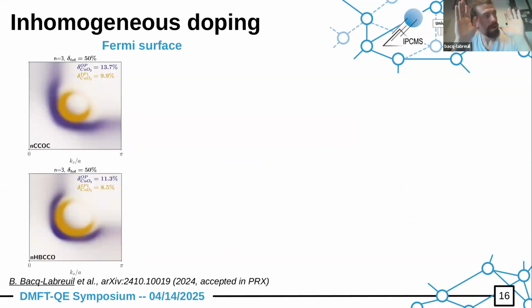Okay, so we have understood quite well what is intrinsic to this system, even before we dope. Now we can look at the normal properties. How do they behave when we dope the system? I think a nice way to see how the doping becomes inhomogeneous is to look at the Fermi surface. Here I plot the Fermi surface of the n=3 compounds on the left, both types of compounds, COC and mercury-based. We can see again the differentiation between the outer plane in purple, and the inner planes in yellow and orange. You can see very different types of Fermi surfaces because they host very different numbers of holes. So the inner planes are much less doped than the outer planes.